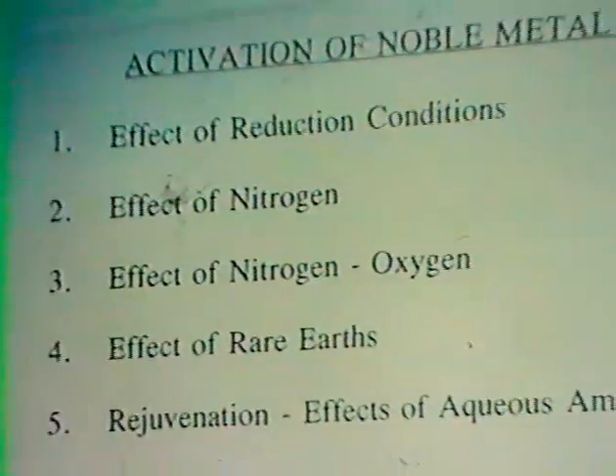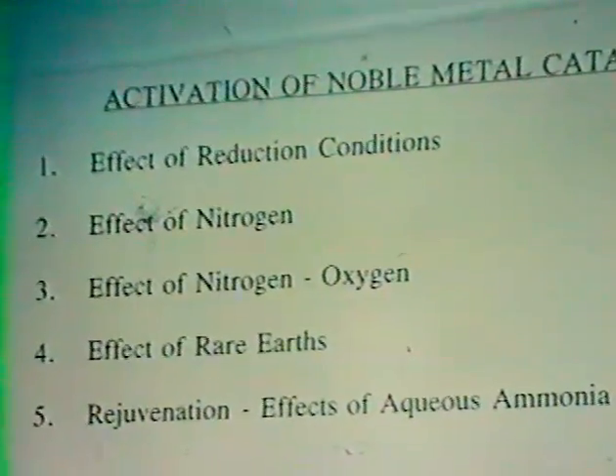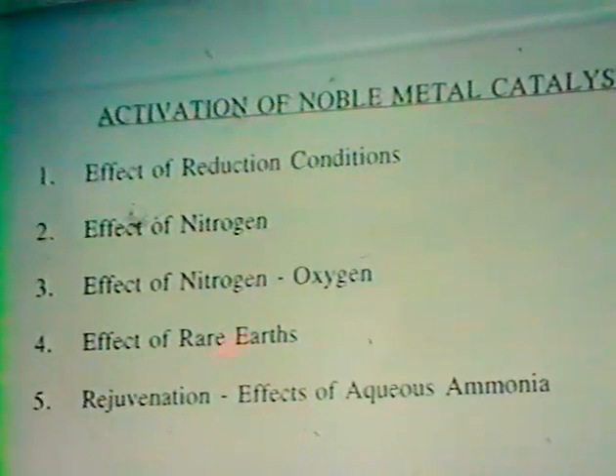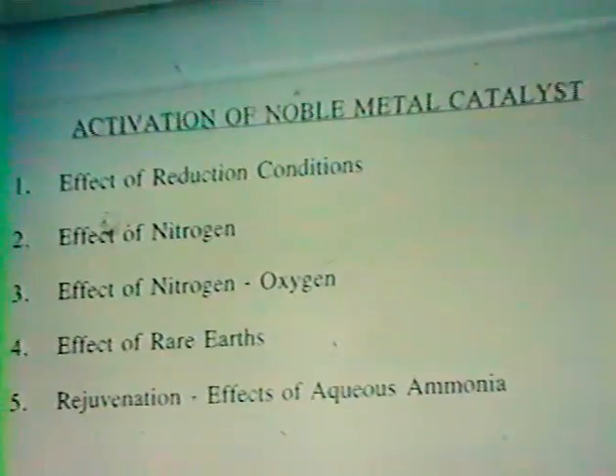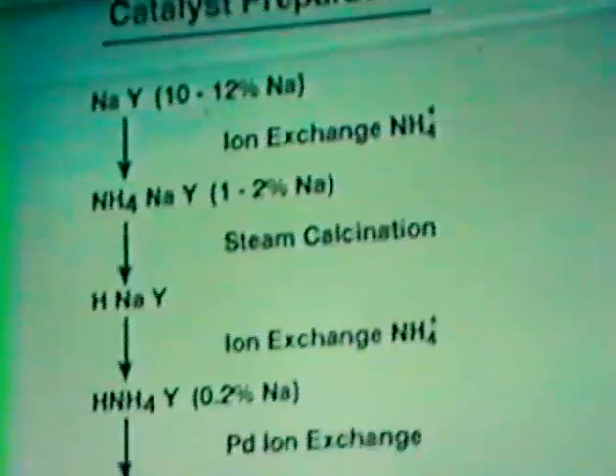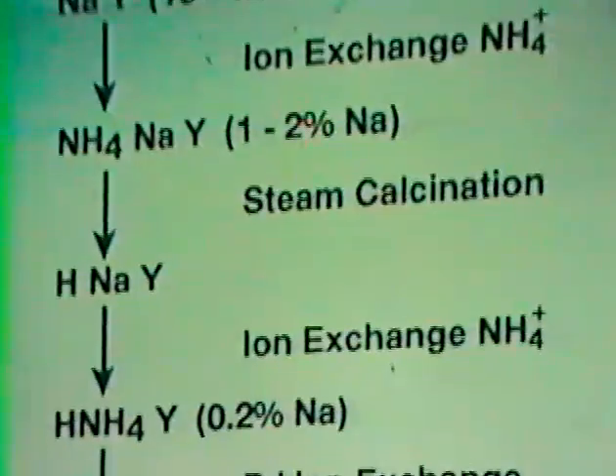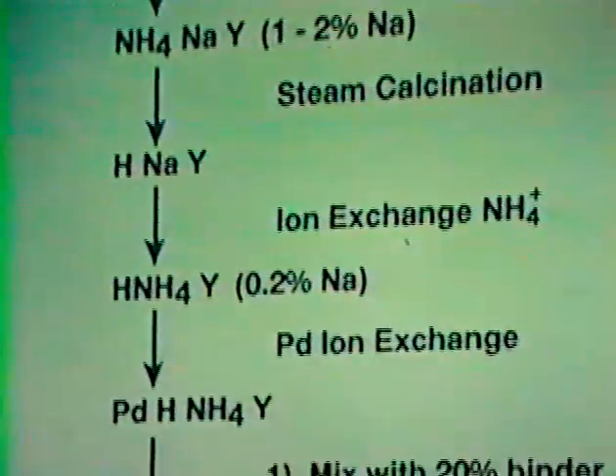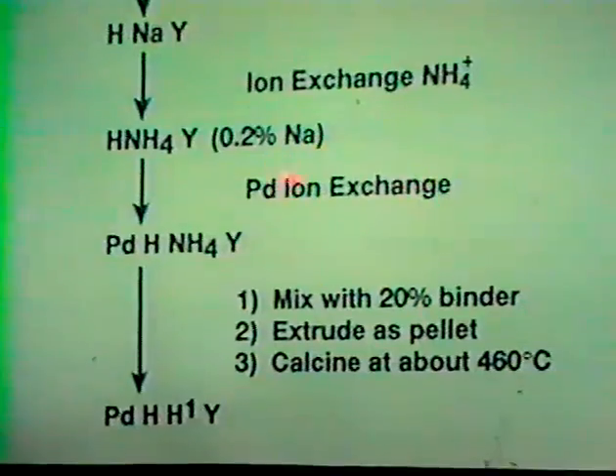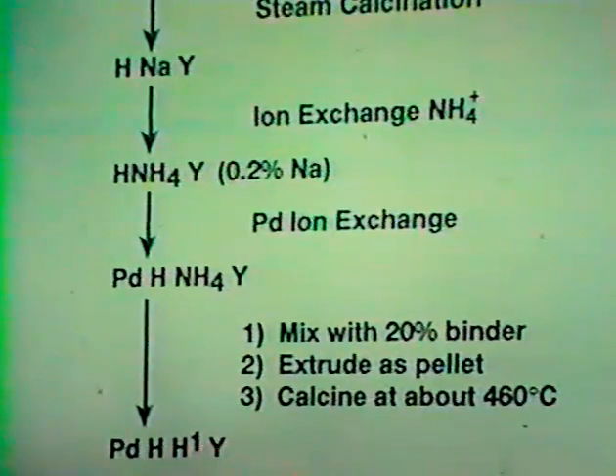Right, now to talk something about the noble metal hydrogenation components. We'll split this into several sections: one, the effect of reduction conditions, effect of nitrogen gas, nitrogen oxygen, rare earths, and some reactivation studies. What type of catalyst are we using in these systems? We're using, in both cases in this study, starting with a sodium zeolite, which is ion exchanged, with about 2% sodium, steam calcined, followed by further ammonium ion exchange, then palladium ions are introduced into this, that's made into finished catalyst and it's calcined. That stage is put into the hydrocracking reactor.